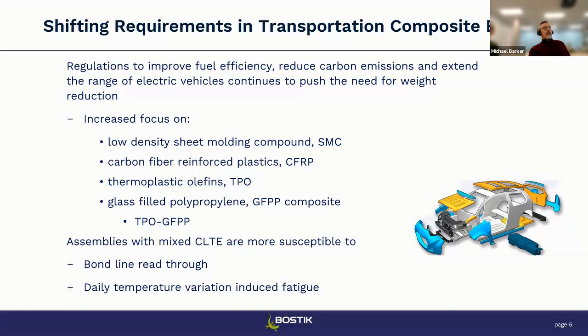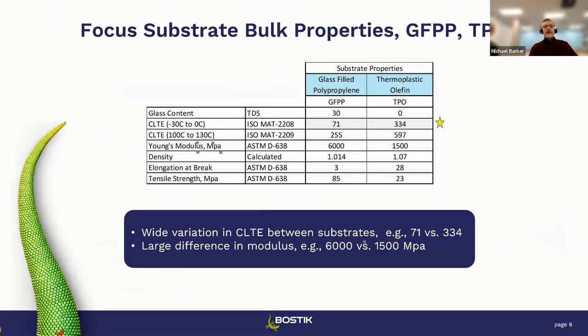And the application that we're going to talk about today is TPO, which will be thermoplastic olefin without glass, bonding to glass-filled polypropylene with glass. And some of the key things that stand out when you're trying to do those type of assemblies is that you have a mixed CLTE, coefficient of linear thermal expansion, and also you can have issues with bond line read through, and of course fatigue. So let me jump into it here a little bit.